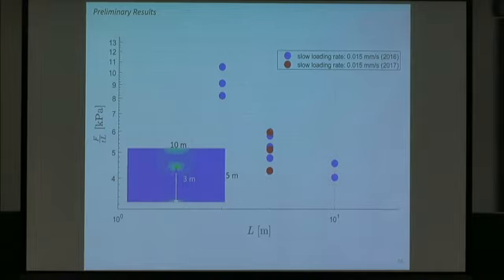And these are the peak force while we load the sample, and the force increases, and then it fractures. And we recorded this peak force and then plotted here versus the size. And they are all of the same loading rate.